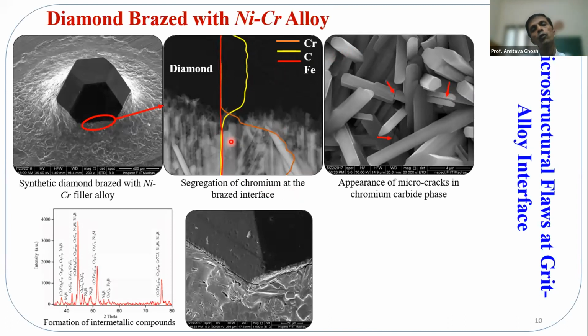When we tried to see what exactly is happening, we wanted to reveal the microstructure at the interface. When we etched this portion out electrolytically, we showed there is a phase called chromium carbide. And there is also a phase which is iron chromium carbide with a typical proportion of the atoms. But these two phases are a bit semi-coherent with the matrix. Because of that, when you solidify it, the stress level increases on this particular structure, and that is exactly existing at the interface. And this chromium carbide is further wetted by the nickel matrix. Now, this chromium carbide itself is ceramic in nature.